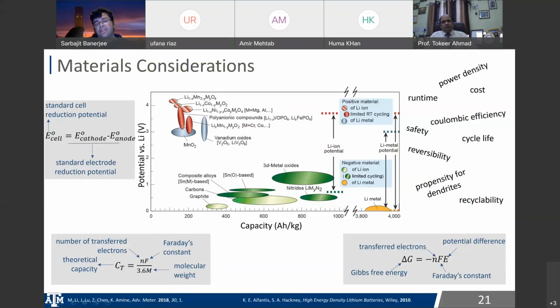And then on the cathode side, there's been lots of progress again in pushing the voltage. These manganese oxides with different dopants are high voltage cathodes, but then sometimes, as you can see here, their capacity is low. So it's not just the vertical axis that is important, which gives you the voltage, but also your horizontal axis, which gives you the capacity, right? As compared to these high voltage oxides, these vanadium oxides here are high capacity cathodes, right? And so I'm going to mostly focus on this. This is where we've done most of our work. Ideally, this kind of tells you what you're looking for.